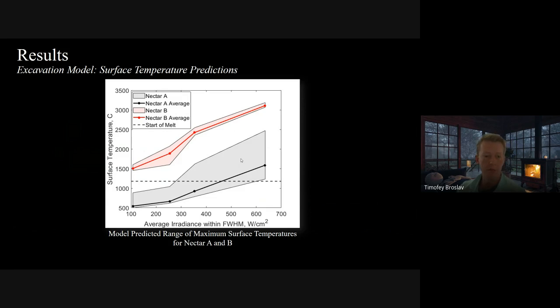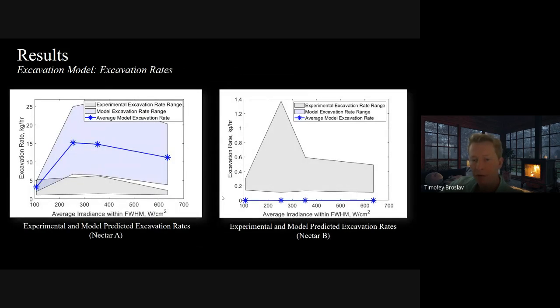I should say this is the maximum surface temperature. There was a range of temperatures; this is just the maximum. And for the Nectar A, the model did predict that there were going to be some areas that would exceed the melting point of the material, though this did not happen until around 400 to 450 watts per square centimeter, which aligns with the drop-off of the Nectar A mining rate.